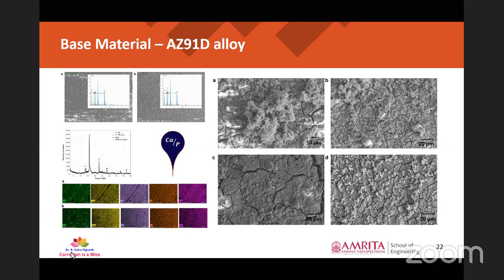So we have taken some EDS analysis first. The EDS analysis confirms that the corrosion product is rich in elements of magnesium, sodium, calcium, phosphorus, chlorine, and oxygen. And added to that, specifically the calcium to phosphorus ratio of these corrosion products changed from 2.15 initially towards 1.65 after 7 days of immersion.